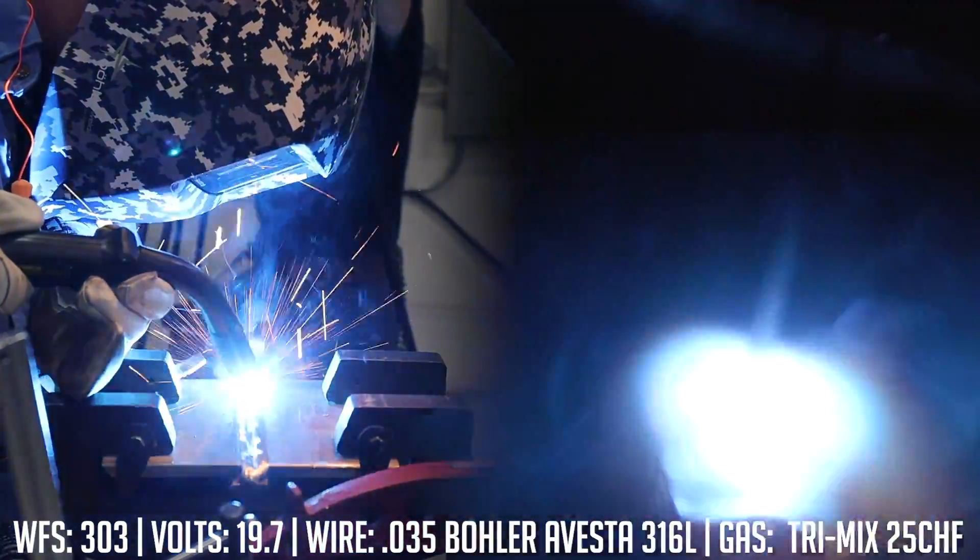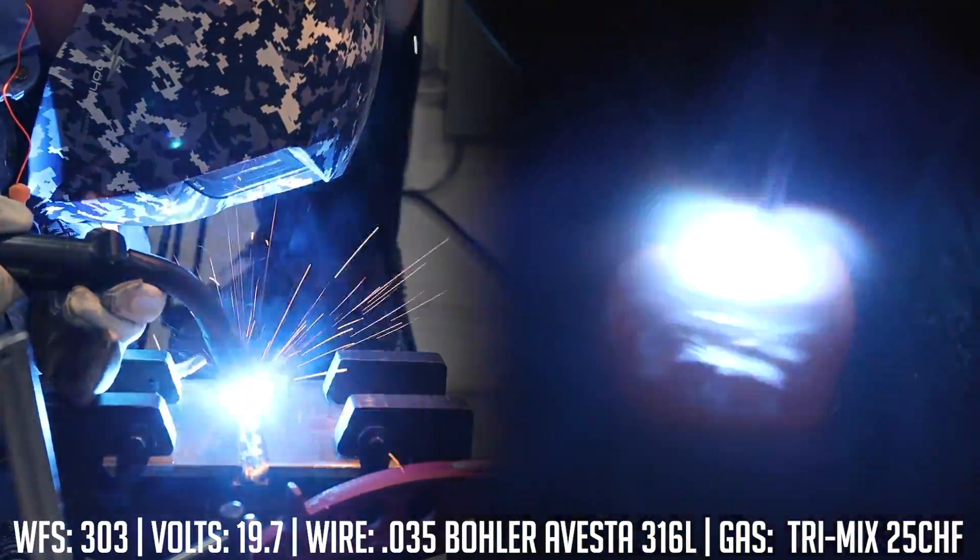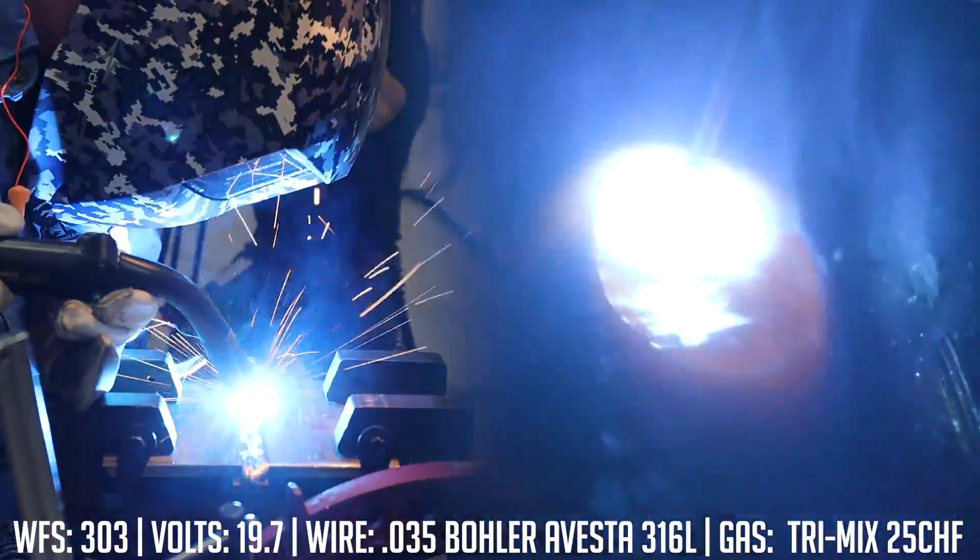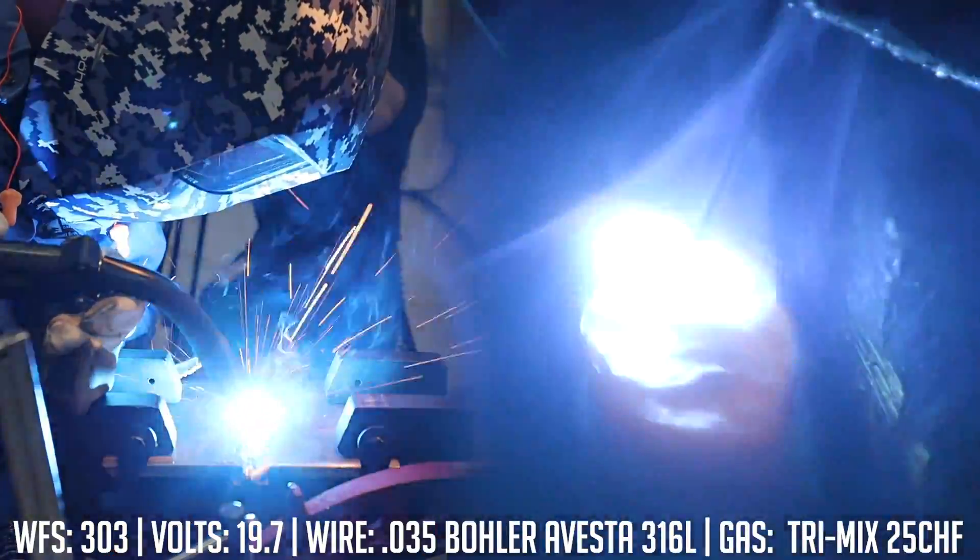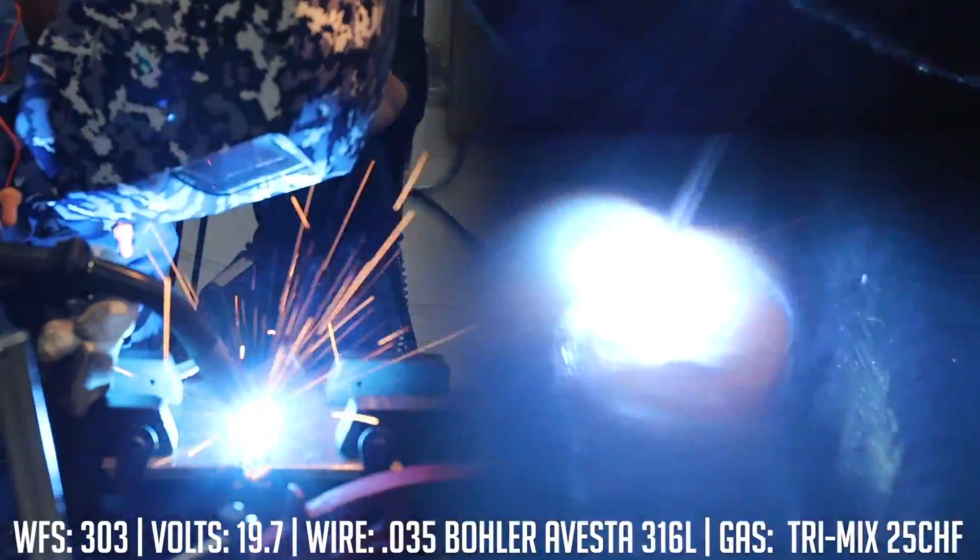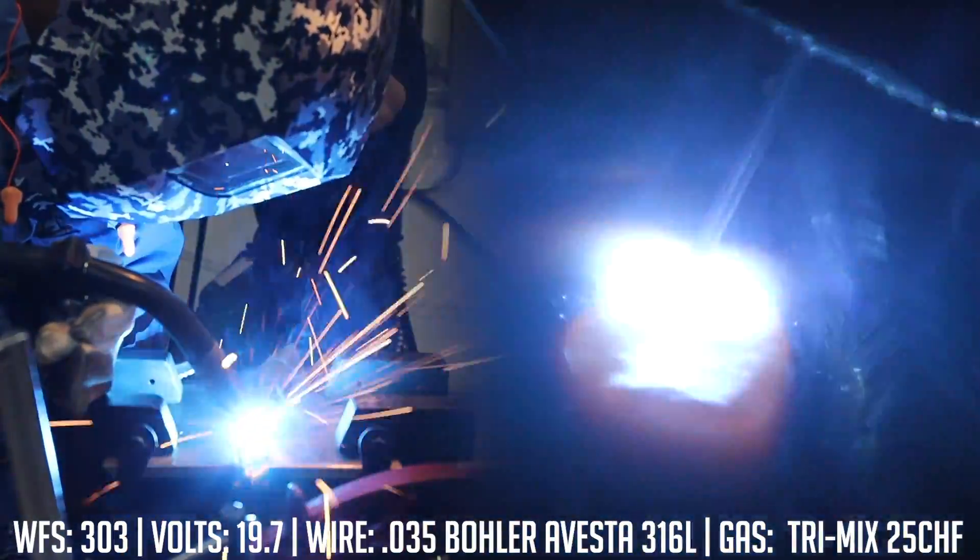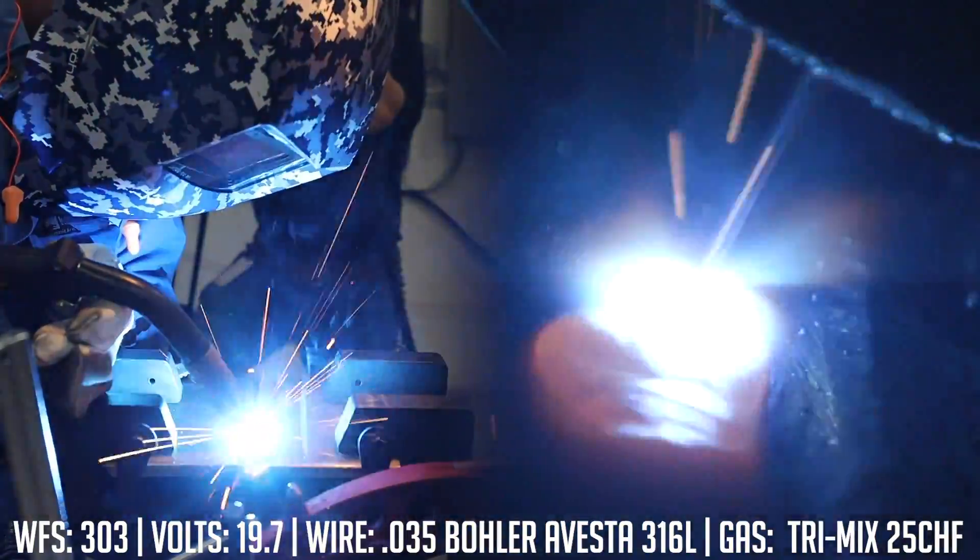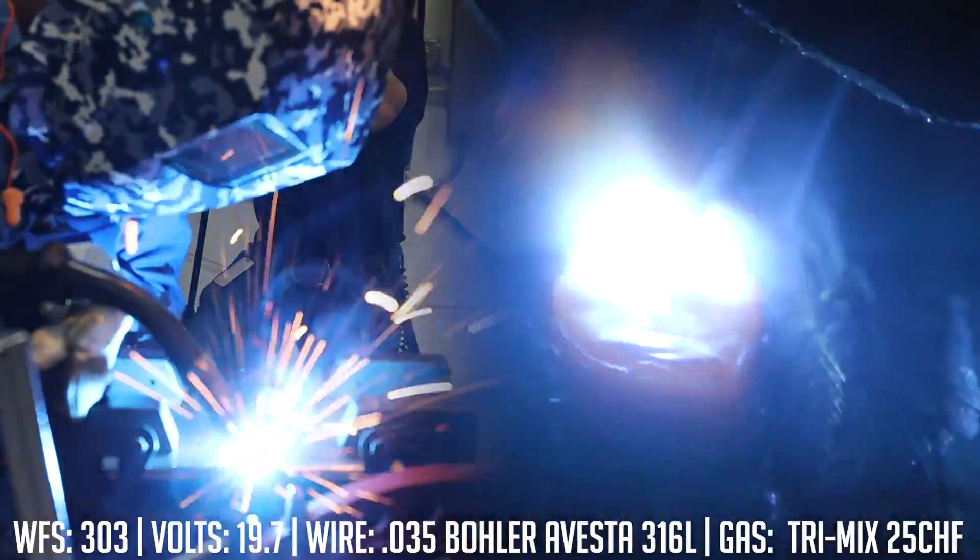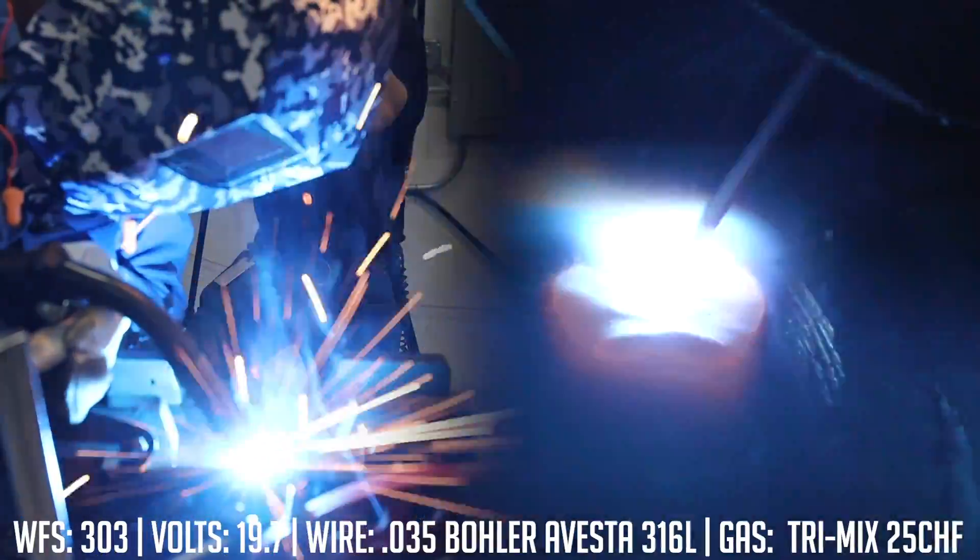We want to make sure our beads are overlapping by half. You want to do a slight hesitation. That's what stainless steel wants to do. It's hard to move, so you want to definitely hesitate over there for a quick second or half a second. You don't have to keep your bottom toe as accurate, because you're going to put a grind mark in there to get rid of your bottom toe. Everyone's going to see your top toe, because you can't fix it anymore. Always weld to the end.